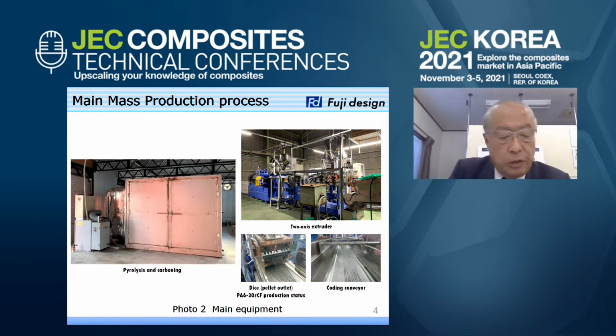The pyrolysis process is developed to control high temperature burnout gas from an LPG burner. Combustion gas is induced into the pyrolytic treatment zone. It means evolved gas from the reacting chamber will return to the burning area, heating the area with a small amount of oxygen from air. As a result, we can save LPG gas consumption. It means we can reduce energy consumption and achieve a lower LCA value.